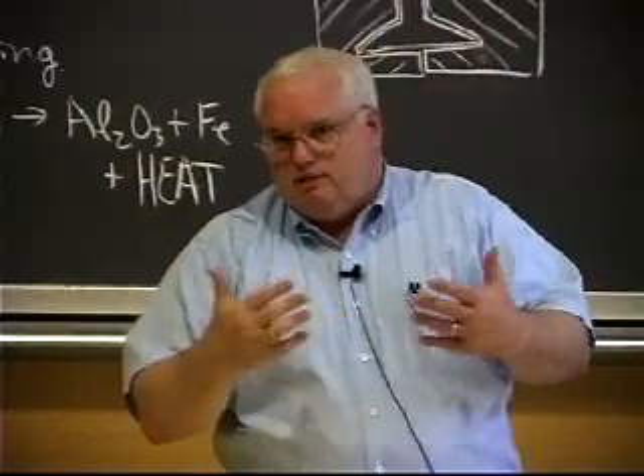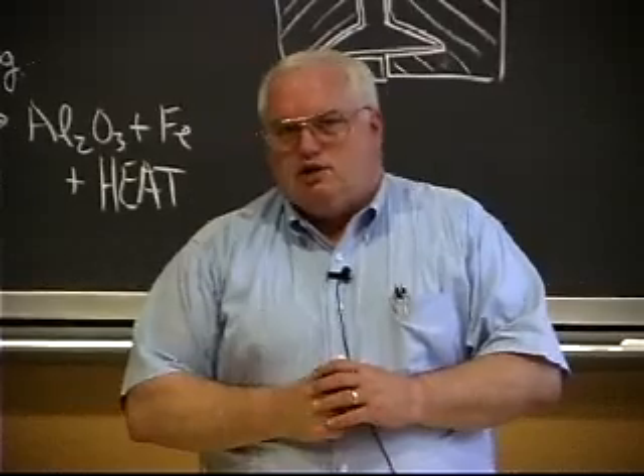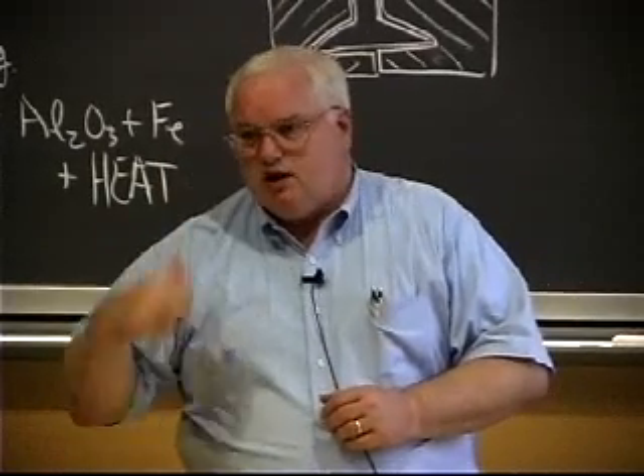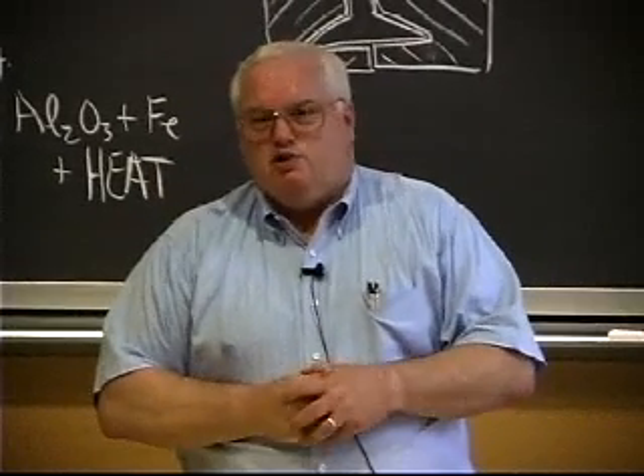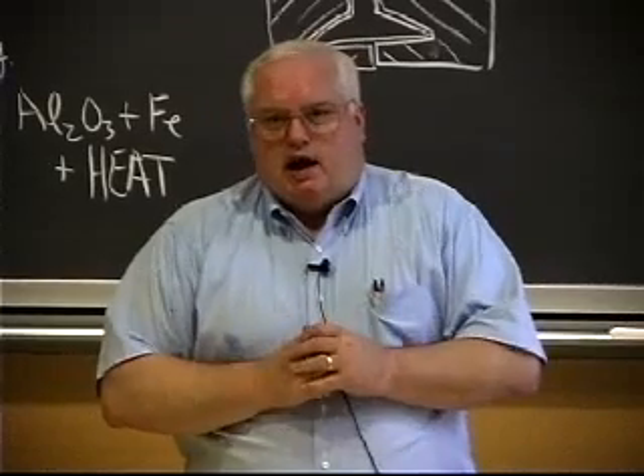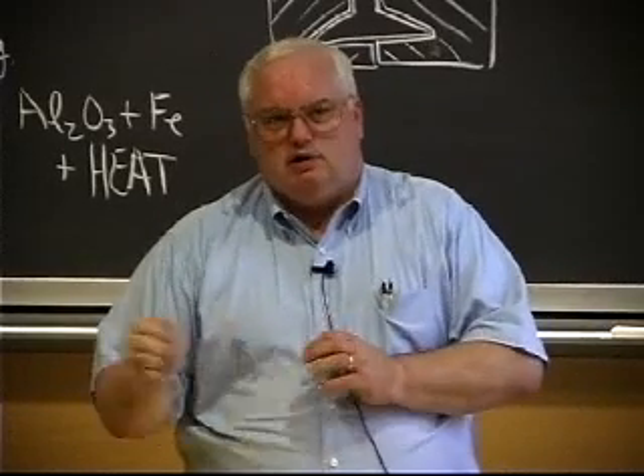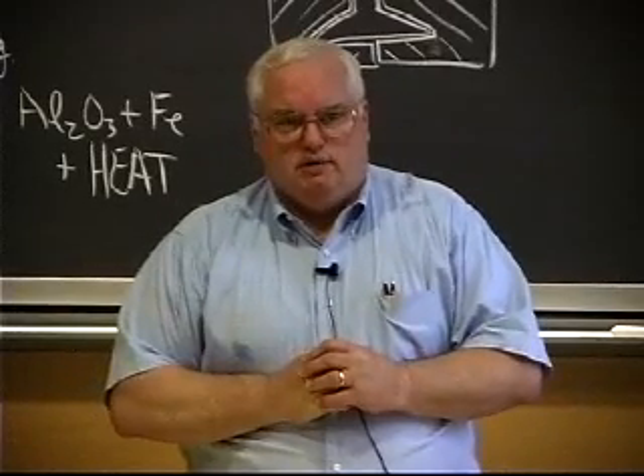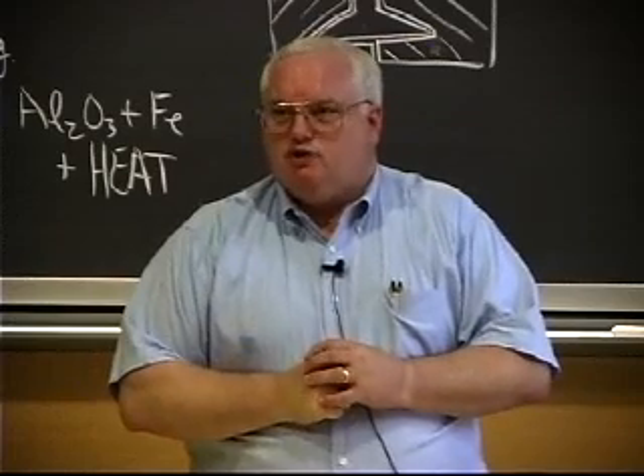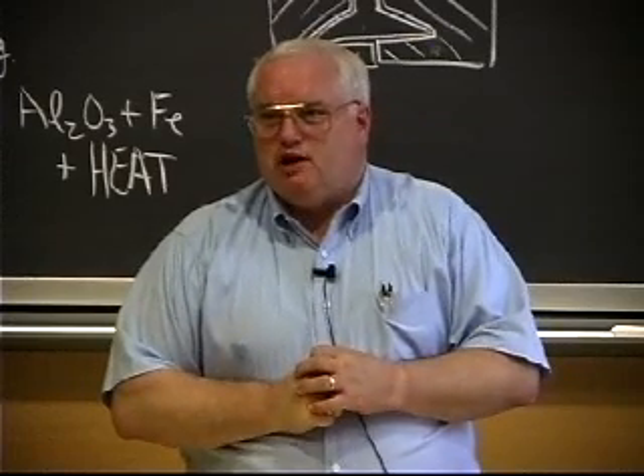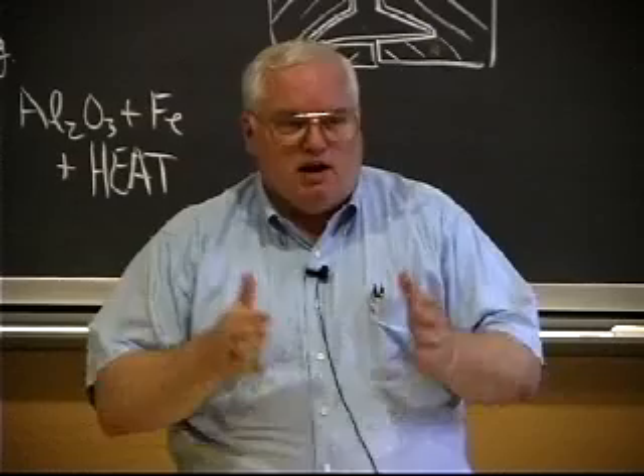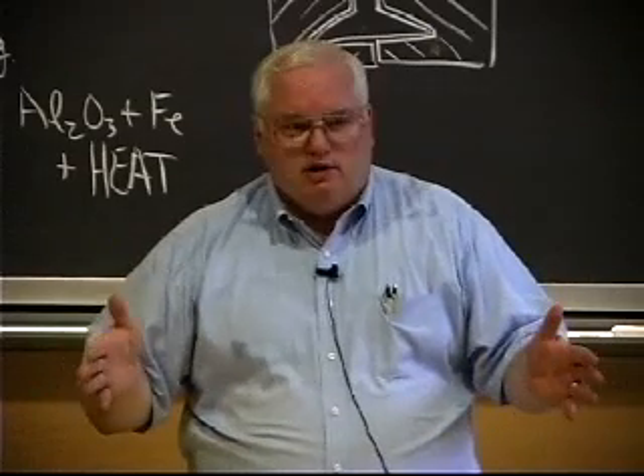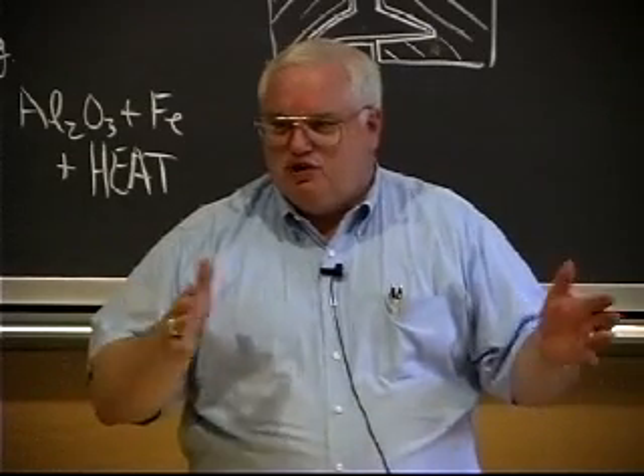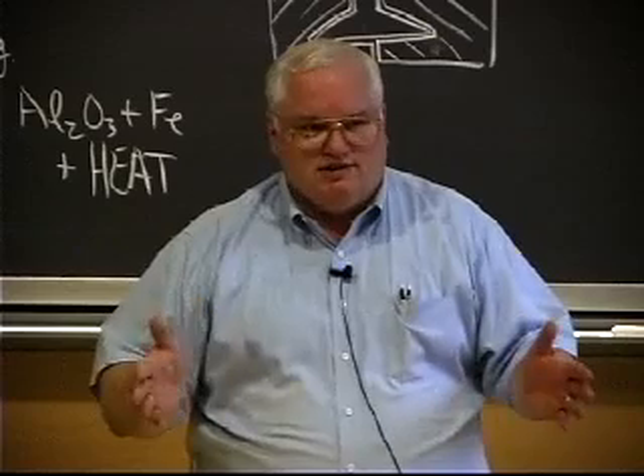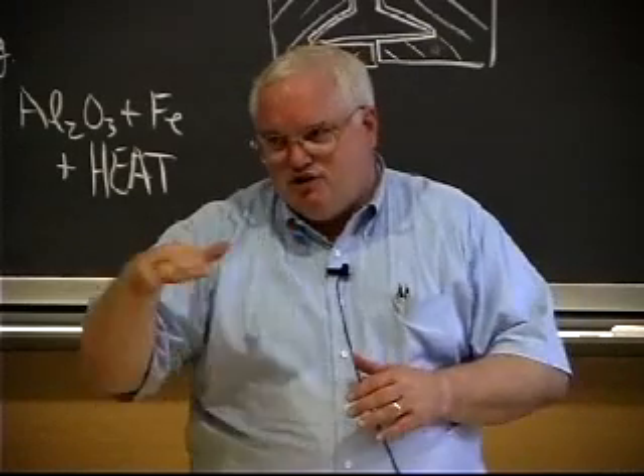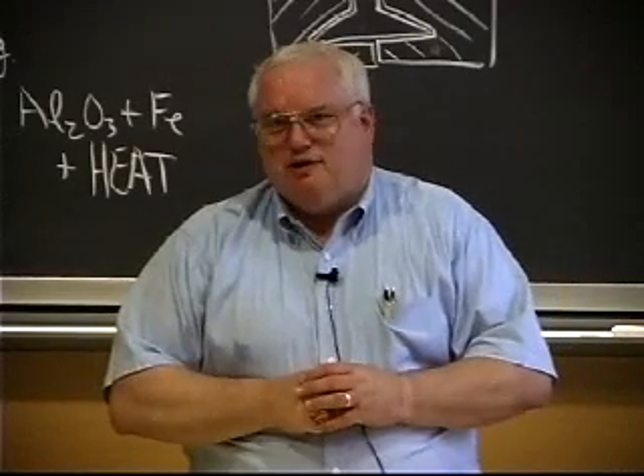And it all solidifies. You wait 10 minutes, some guy comes along with a sledgehammer, knocks the sand off, some guy comes with a grinder, and you grind it. And then you have a guy come in with an ultrasonic tester to see if the joint's any good. And half the time, the joint is good. 50% of them are junk. And so you have to cut it out and put 2 more joints in, of which each one has a 50% probability of success. So you can see this is not converging quite as fast as you would like, okay?